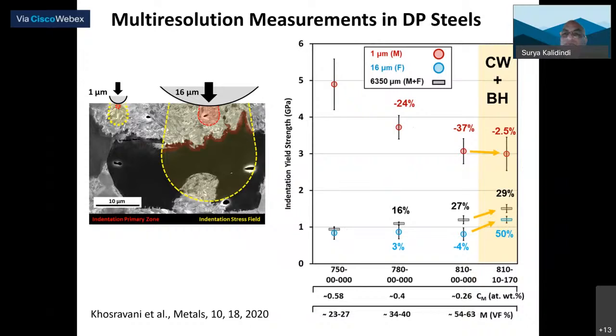But in this particular case, what we're showing is that as you increase the annealing temperature, the martensite is actually getting softer, a pretty strong drop in the local strength of the martensite. But on the other hand, the ferrite is more or less constant. Nothing is changing in the ferrite itself, the blue. The effective value is actually increasing. Although the martensite is getting softer, the bulk value is increasing. That's because the volume fraction of martensite is increasing. So although martensite is getting softer, the volume fraction is higher, so the effective value is going up.